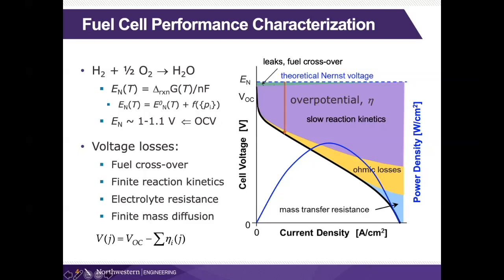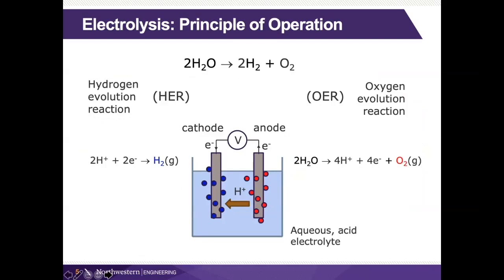So again, we operate typically at around 0.7 volts, which would be lower than the peak power. And one way that we describe our fuel cells, however, is always by this peak power density, because that's an easy single metric to compare fuel cells to one another. Now, again, electrolysis is simply doing that in reverse.